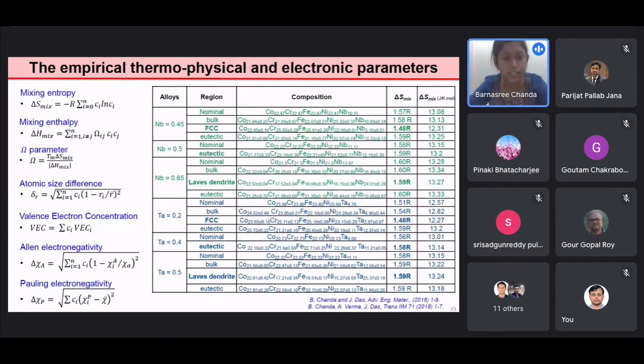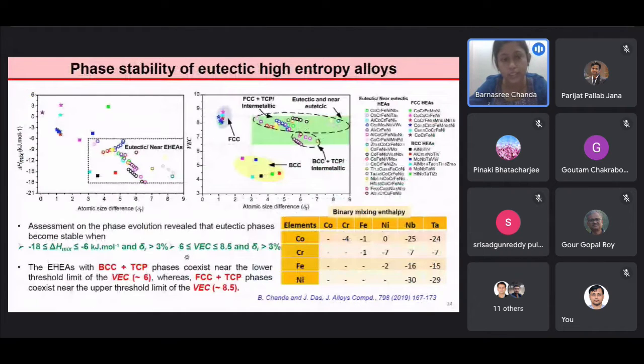Further, we have plotted the mixing enthalpy versus atomic size difference, and we compare it with the single phase FCC and single phase BCC high entropy alloys, where we see that the eutectic and near eutectic high entropy alloys are stable in the range of -18 to -6, and when the atomic size difference is greater than 3%. Which is quite reasonable because a positive value of mixing enthalpy leads to phase segregation, and a higher negative value of mixing enthalpy leads to the formation of intermetallic phase. Therefore, a moderate negative value may promote the formation of the two-phase eutectic composition.